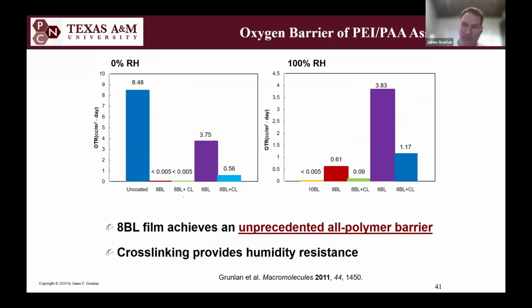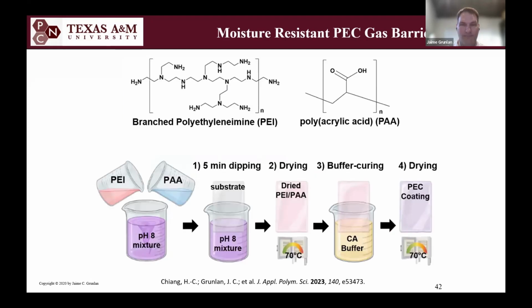Once I deposited 10 bilayers, and maybe that was 2 microns thick, you couldn't detect it even at 100% humidity. It was so highly ionically cross-linked, so dense. It has a modulus above 10 gigapascal as just a purely polymer thin film. So that was pretty exciting when that first came out. You can see that it was published in 2011. That was a while ago.